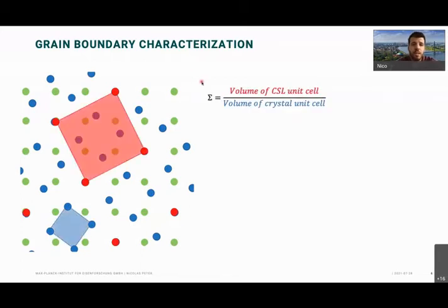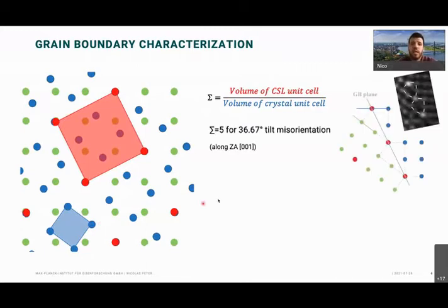And now people like to characterize grain boundaries by a sigma value, which is the volume of this CSL lattice, the red points, divided by the volume of the crystal lattice, which is, for example, the blue or the green points. In this case, it's the same. So what we are talking about today, and this is just an example of this, is the sigma 5 grain boundary. In this case, you give a tilt misorientation. So you tilt one crystal by 37 degrees.